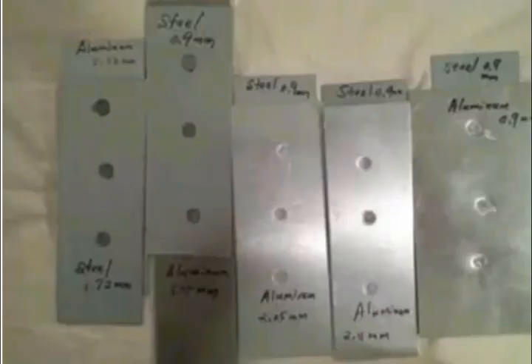A few years ago when I tried to weld mild steel to aluminum, the first weld melted a hole through the aluminum and destroyed the electrodes. But when I tried to weld aluminum to galvanized steel, it only took me 30 minutes to find the right weld schedule and welded 5 coupons. The only difference between mild steel and galvanized steel is the zinc layer. I later found out the zinc layer changed the normal resistance welding to transient liquid phase welding and helped to